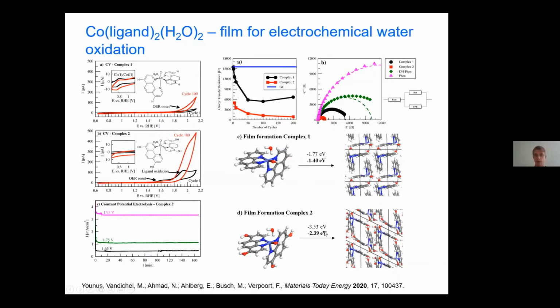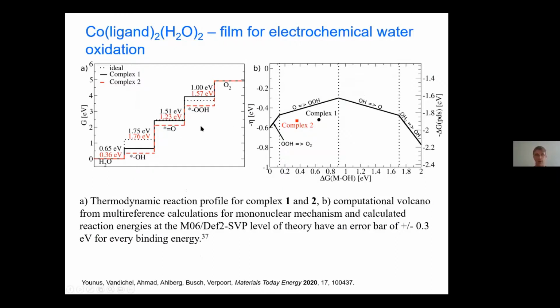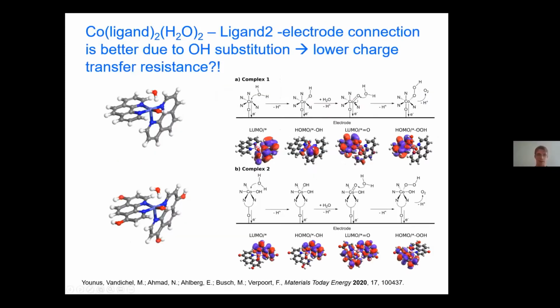So in bold, that's the value with solvent correction, and that's the value without solvent correction. But if we look at things computationally, the overpotential we get is very similar for complex 1 and complex 2. So clearly that does not explain so much why complex 2 has a lower charge transfer resistance. And then to explain the charge transfer resistance, we can maybe hypothesize that it's the connection between the hydroxyl group and the glassy carbon electrode